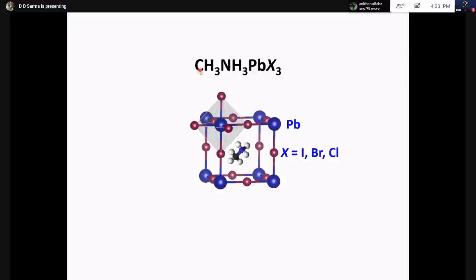And this A site is occupied by this particular organic material, methylammonium, which you put in the body center position, which is the A site. And that gives you the essential perovskite structure. You can see the structure can be described as this Pb coordinated by 6 iodines around it, giving you a PbI6 octahedron. And this octahedron is connected corner-shared, because this iodine is common between this octahedron and the octahedron